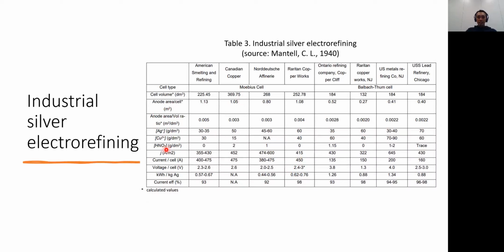And in this electrorefining process, as you can see, the silver content is like 30 to 60 grams per liter. This is very low. And the free acid content, some refineries have none, 0. And some have 1 gram per liter, and then 1, 2. So the amount of free nitric acid there is kept low because it can dissolve again the pure product of the process. It runs at a current density of 300 to 400 amps and sometimes 600. But my dissertation proves that we can go up to 1,000 without any problem. But we can check it later on.